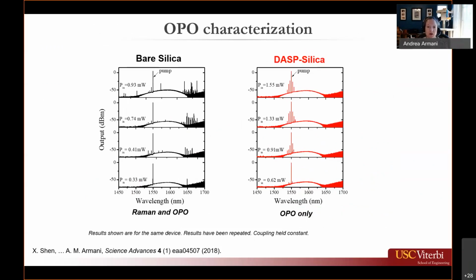Okay, so when we look at the spectra, when we have a bare silica device and we input anywhere between 0.3 milliwatts to about 1 milliwatt, we were unable to see really clear four-wave mixing. We got a lot of Raman generation. Depending on the stability of the coupling, so how much thermal vibration we saw, the Raman could end up getting really messy. One of the challenges with microspheres is that because they have a lot of very dense modes, every one of the internal resonance modes can generate a distinct Raman signal, and that's why you end up with Raman spectra that look like this.